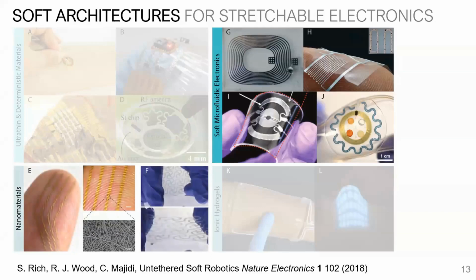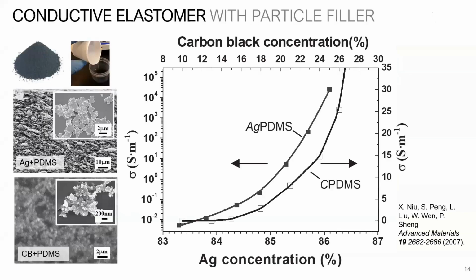And so, basically, we took a step back, working with our collaborators at Coimbra in Portugal. So this is Mahmoud Tavakoli's group. We thought, okay, let's not be so dogmatic with using just liquid metal in elastomer, and let's try to incorporate what's traditionally used in printed electronics and start working with some of these nanomaterials. In particular, taking some of these silver nanoparticles, silver microflakes, and then blending that with the rubber and the liquid metal.